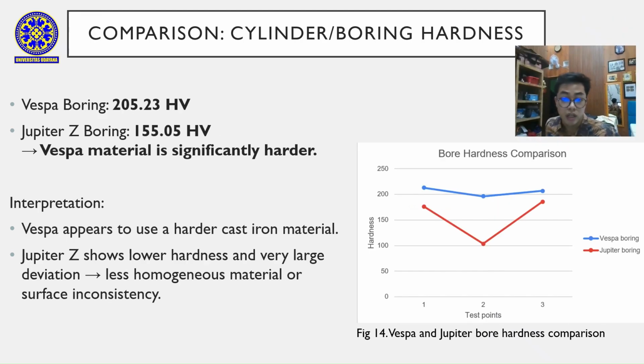In contrast, the hardness of the cylinders or the boring shows a clear difference. The Vespa cylinder is significantly harder at 205 HV, while the Jupiter Z cylinder is only around 155 HV. This may indicate the use of harder cast iron material in the Vespa, or simply better material consistency. The large variation in Jupiter Z's boring hardness suggests possible differences in casting quality or microstructure.